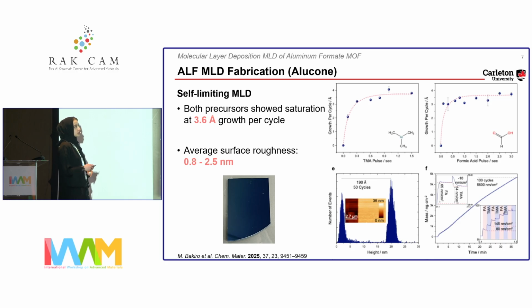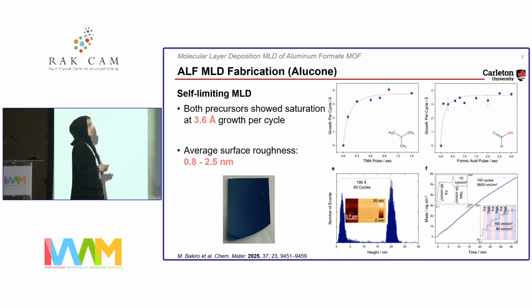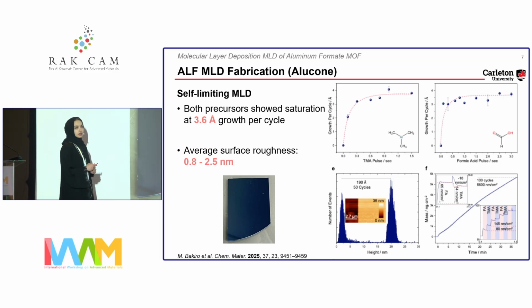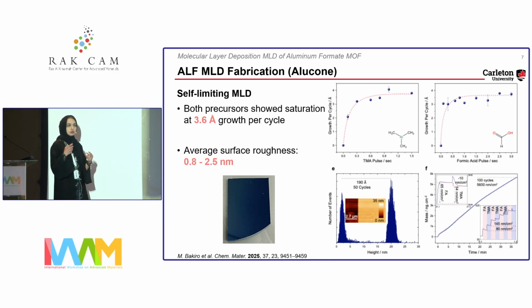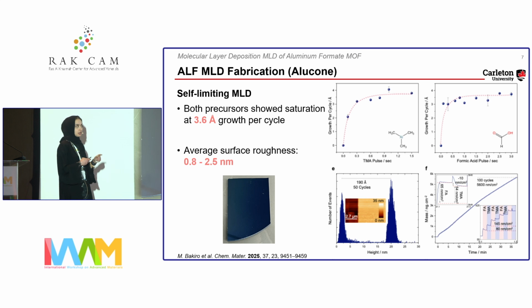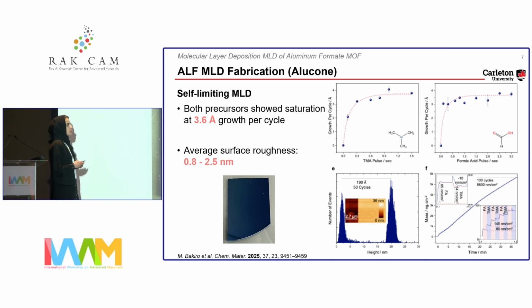For every saturation curve, you have to set one of the precursors stable, the pulsing stable, and then you have to vary the concentration of the other precursor. What you want to see here is a plateau in the thickness, because no matter how much you increase the dose, that should never increase the thickness even further, because we're talking about an atomic layer at a time, right?